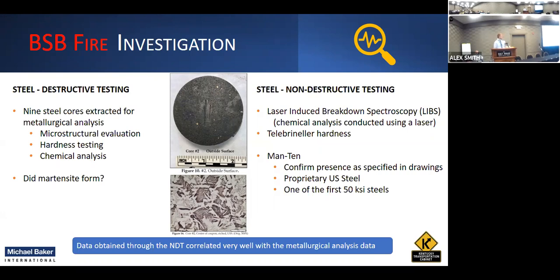So we did several cores looking for the martensite. We also did a significant amount of non-destructive testing. The philosophy on that was, if we can take some small samples and understand the properties of those and know what's happening, we can then do non-destructive testing over a much larger area. Not knowing whether we could take the cores at the absolute worst location, if we could correlate the destructive testing from the cores we did take to the non-destructive testing over a larger area, we'd have a higher level of confidence.